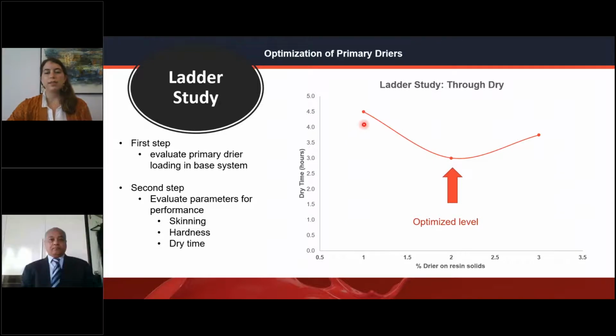Here we have an example where 1%, 2%, and 3% Borchi OXY-Coat was tested on resin solids. If you would have started at 1%, you might not have met the dry time needed if your goal was 3 hours in the short oil. Testing at 2%, you received a faster dry time and met your goal, but we don't have a linear slope where adding more catalyst gives you faster dry time. Actually, by overdosing, you have the risk of negatively affecting your dry time. It's a very different mechanism with these driers.